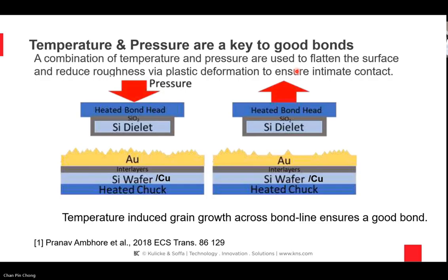This work was done both on gold surfaces as well as copper surfaces. Gold will bond at a slightly lower temperature because gold is a softer material compared to copper, and that helps a little bit. For most of the III-V materials that we do, we thermally compression bond with gold, but for the silicon-based materials, we do it with copper. Next chart.